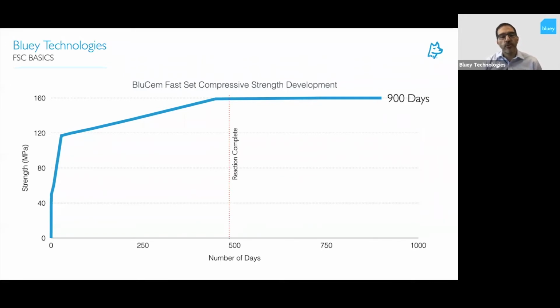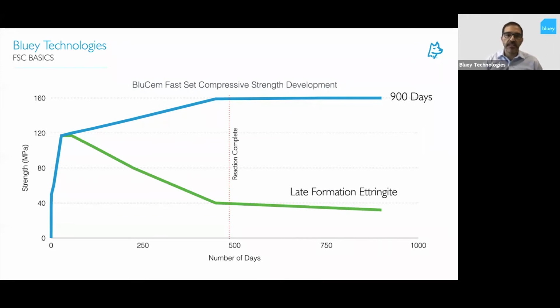So what we want to make sure of is that the actual reaction that's occurring between 28 days and 500 days isn't having a negative impact, because we know that that's when ettringite is forming. And if you have an oversupply for that ettringite crystallization, then it can break down your cement structure. And if that breaks down your cement structure, then it can lead to a reduction in strength over time. And this has been seen, if we go back maybe a decade, 2 decades ago, in some CSA systems where the strength gain after a couple of years was noticed to drop off and there was powdering of the surface and a reduction. So this is something we avoid by doing the long-term testing.